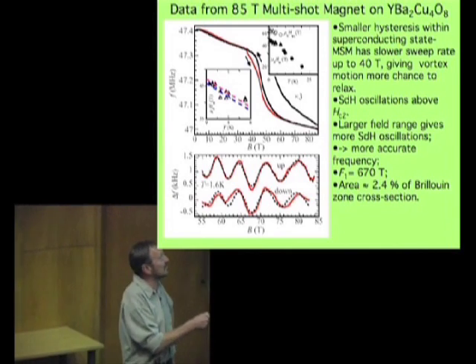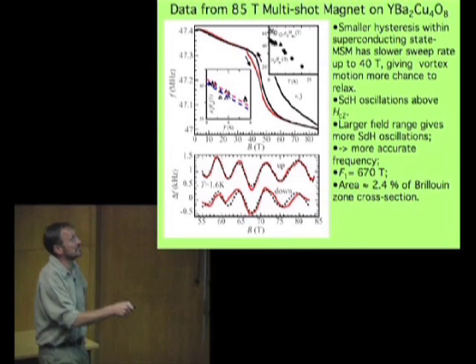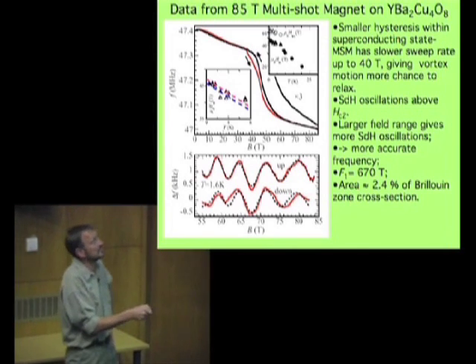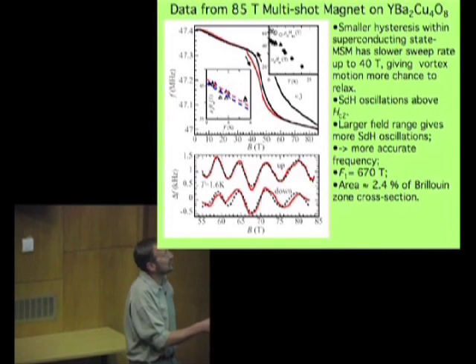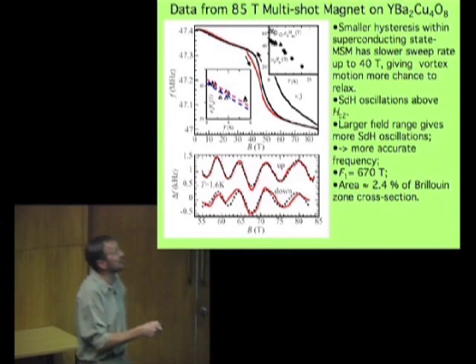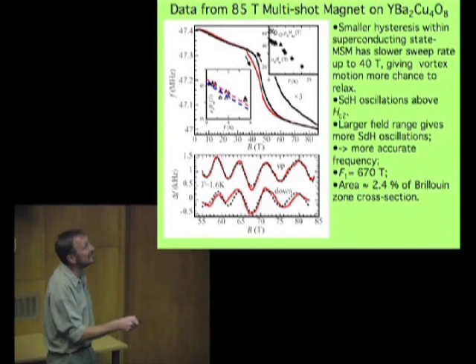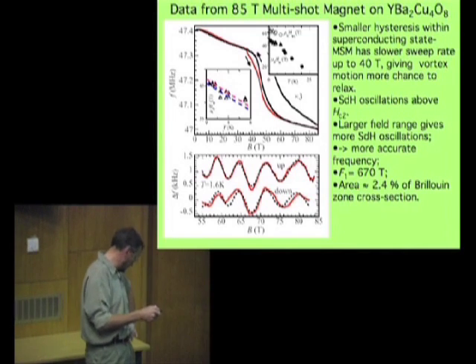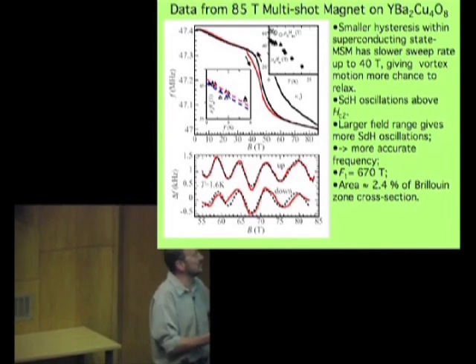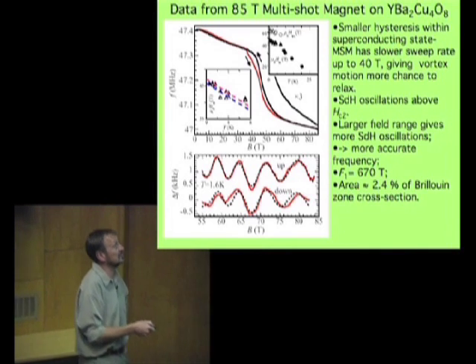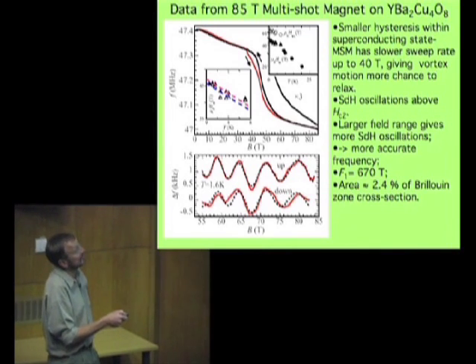When we do a background subtraction, now you can see that we have several oscillations and we can work out a frequency fairly accurately. Remember, these things are periodic in 1/B, so frequencies are in Tesla, and this corresponds to an area of about 2.4% of the Brillouin zone cross-section, 2.4% of the unit cell in K-space.